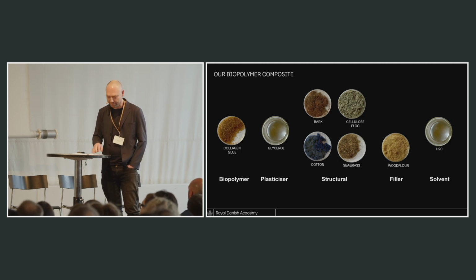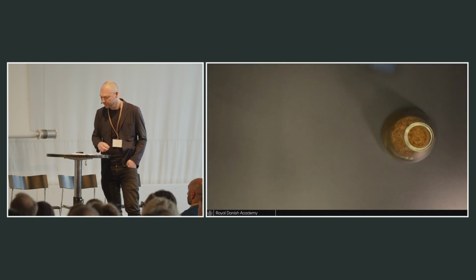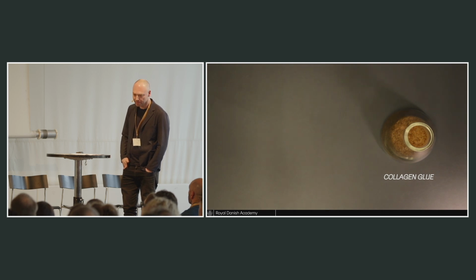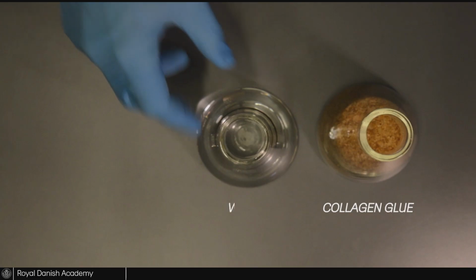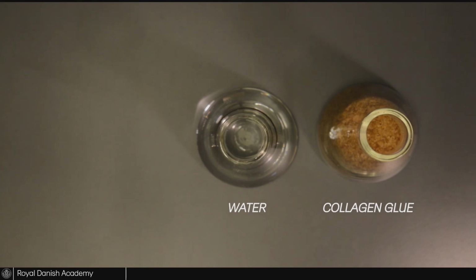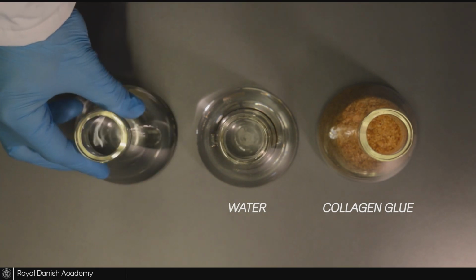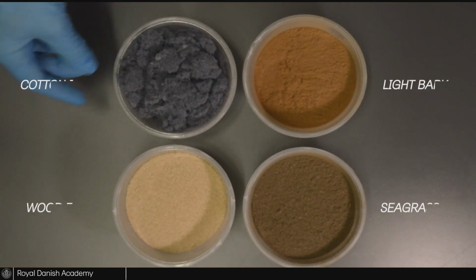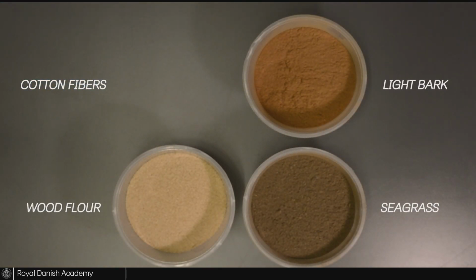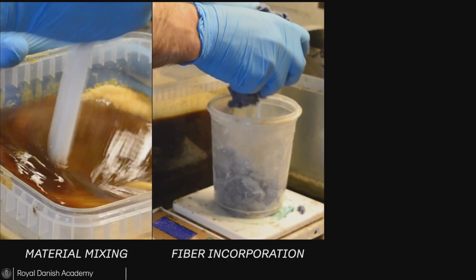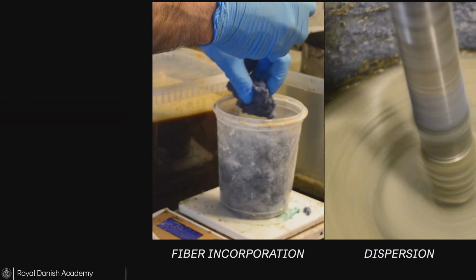Almost anything that we have been able to find has been tested through this material system. With the addition of water, heat, and glycerol, this material takes on a thermoplastic-like behavior, which is quite rare for biopolymers. This means that we can heat that material up, disperse fibers and fillers into it, and then 3D print it using a heated extrusion system.